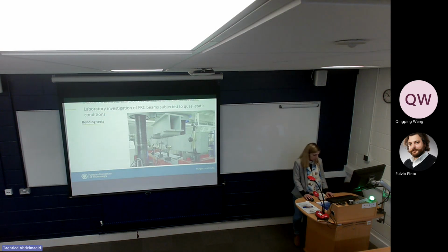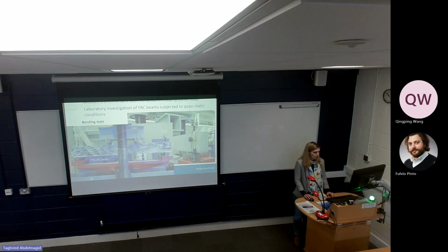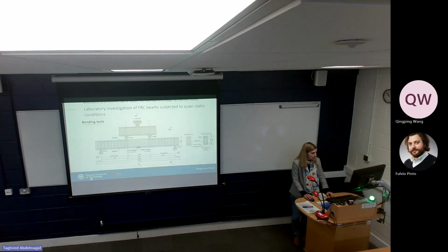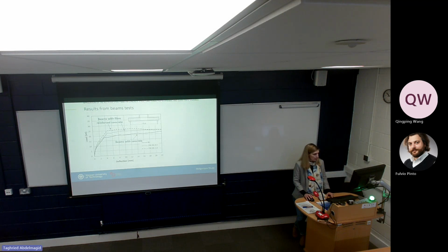And now the bending tests. We have performed tests of bigger beams. It was a huge part of the tests. I will show you just some part, where the beams were reinforced with longitudinal bars. We were of course testing the deflection. We were also testing using digital image correlation. We wanted to see what's going on at the surface of the beam, so how the strains are developing in the elements with fibers and without fibers. This is the cross-section and the project of the beam. This was the part where we should see the results of the usage of the fibers.